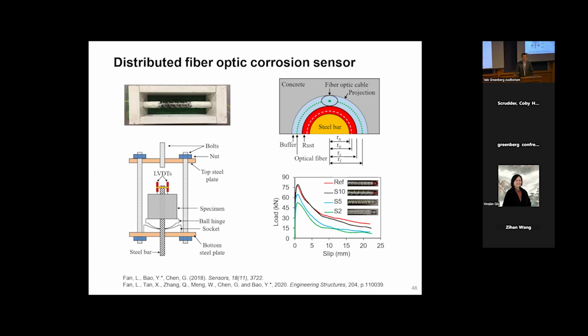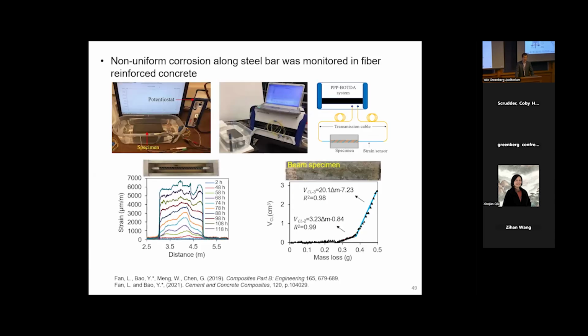But structural engineers were concerned, hey, we don't want to wrap some cables on the surface of the steel bars because that will reduce the interface bonding, right? So then we did some pull-out testing. We showed that when the spacing of the cable is not smaller than 10 millimeter, which is about half inch, then we are okay. But in real application, we can even increase this spacing to reduce the cost.